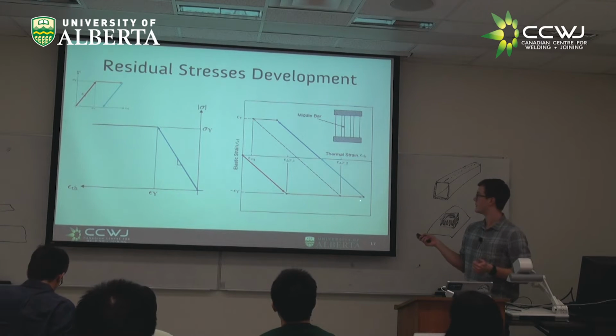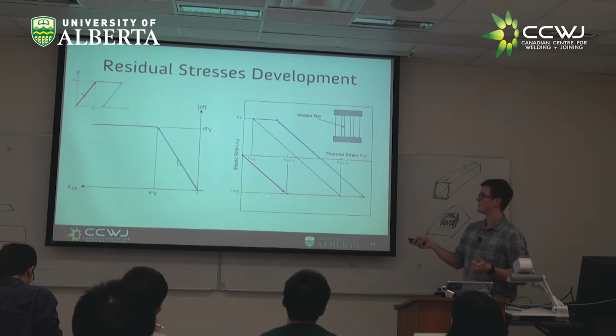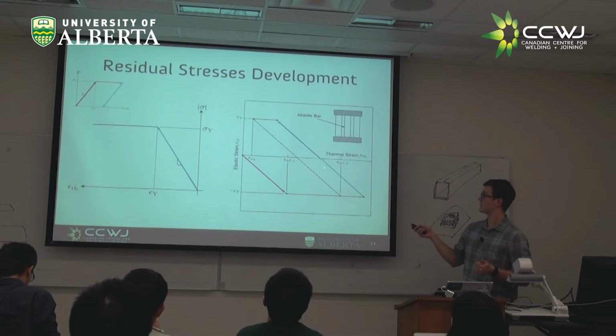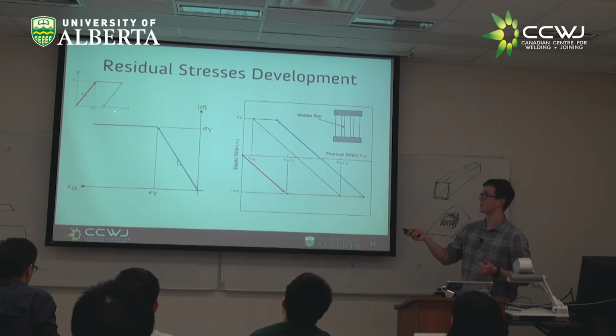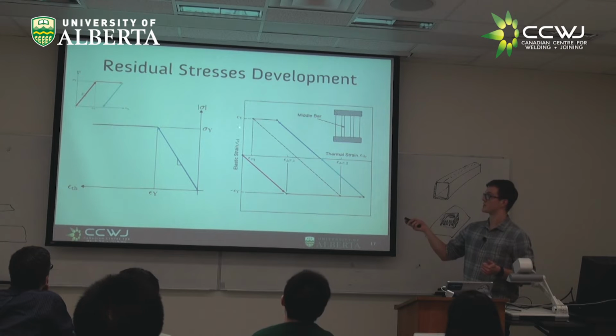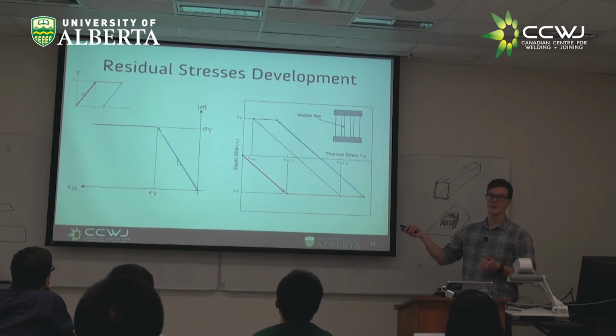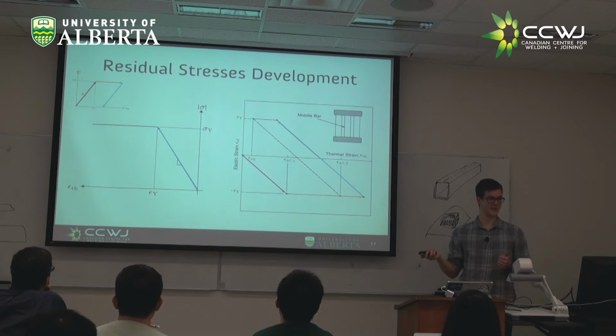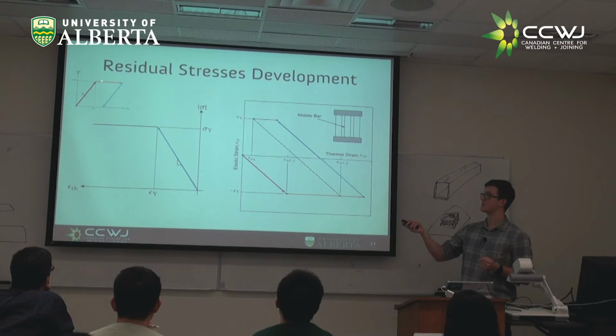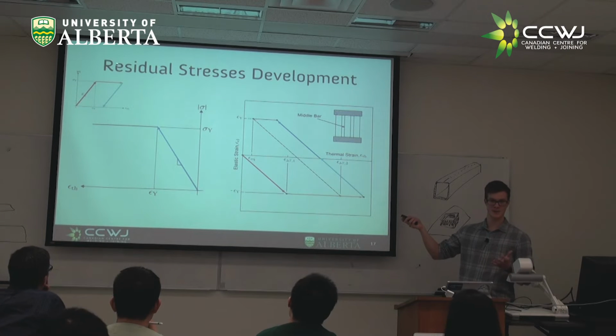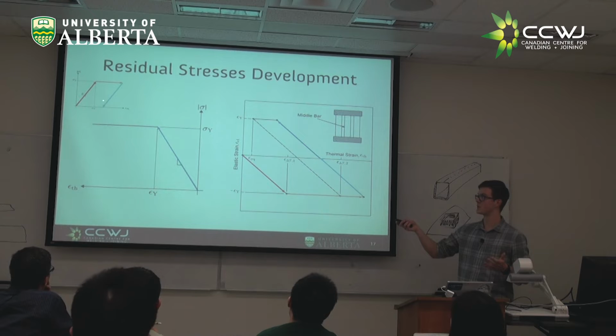Now, what's interesting about this point is that as you cool back to our zero stress state, and then as we go beyond that zero stress state and cool, still moving back towards our initial temperature, we reach some point where we've now yielded again. So we yielded in compression upon heating. We kept heating, we developed all this plastic strain, all this thermal strain, and as we cool, we actually cool enough that we yield again in tension.